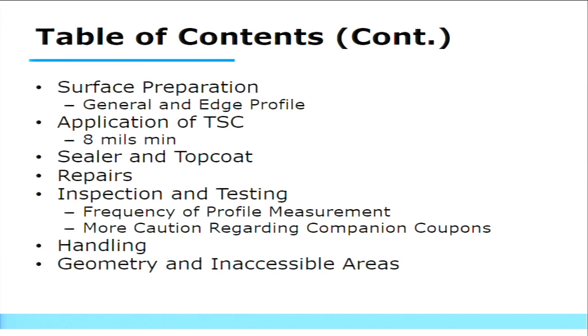Section on handling, geometry and inaccessible areas. One of the downsides to metalizing is for very detailed parts. It can't get behind crevices, double angles, and cross frames. It's going to have a problem with that, and you might have a weak point there. So one of our recommendations, I think it's in this section, is if you're going to do metalizing, and this is in no way an endorsement of doing it, but it's a good system if done properly, is if you metalize the girder, but hot dip galvanize the cross frames. Because the cross frames are a very detailed part, and that's something where you may have problems if you actually try to metalize it.